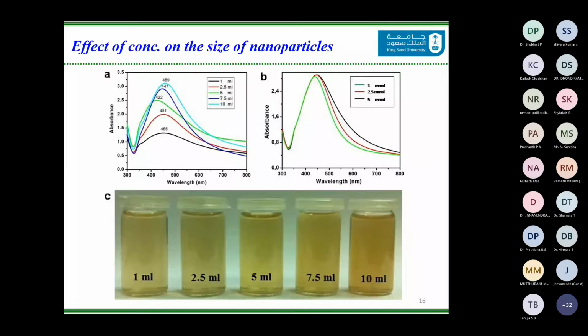In section B of the same image, you can see that a comparative study was carried out to investigate the effect of silver nitrate concentration. We have used 1 millimolar, 2.5 millimolar, and 5 millimolar of silver nitrate solution. How did we do it? We kept the plant extract at 7.5 ml and varied the silver nitrate. We found that when 1 millimolar silver nitrate was used, we got a lambda max of 447 nanometers, while when we used 5 millimolar, it was 455, indicating that as we increase the silver nitrate concentration, the particle size was increasing.